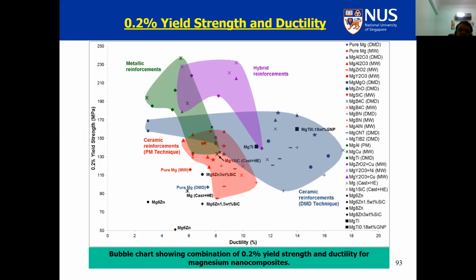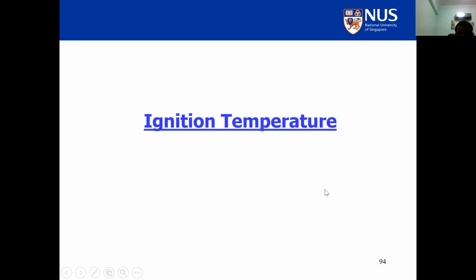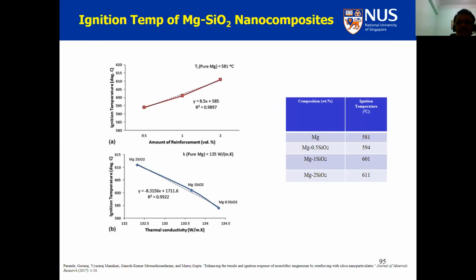You can choose a type of processing from this kind of chart and simply take it to the industry. Ignition: a very big misconception in the scientific and the normal community is that magnesium can catch fire. But to note, magnesium can ignite when it is taken to a temperature of 581 degrees centigrade.